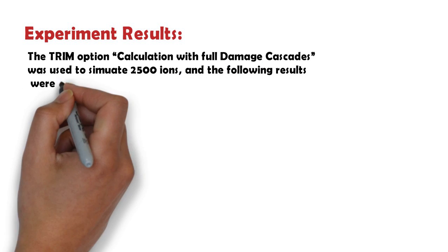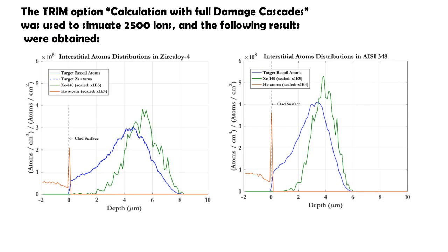First, the green curves describing the ion distribution show that ions penetrate deeper into zircaloy than stainless steel. The projected range in zircaloy was found to be 5 micrometers, as compared to 3.7 micrometers in stainless steel. As a result, the distribution of interstitial atoms given by the blue curves shows that target recoil atoms are more deeply distributed inside zircaloy than in stainless steel.